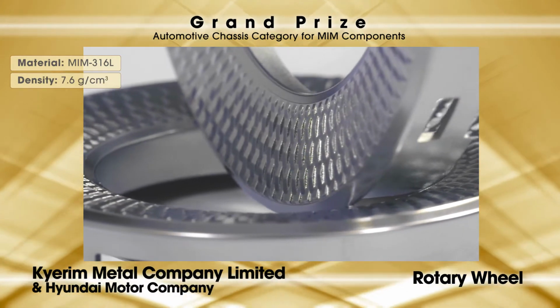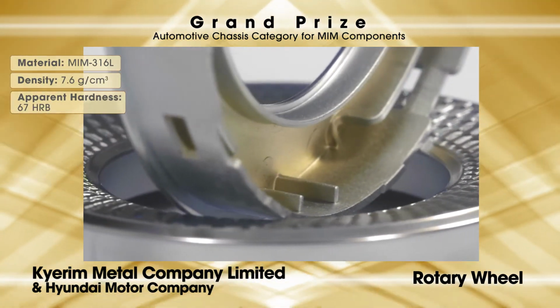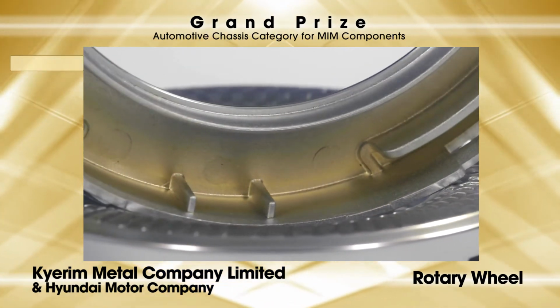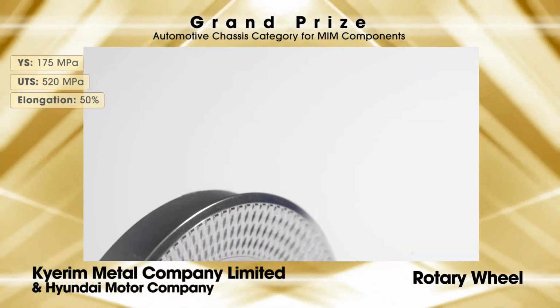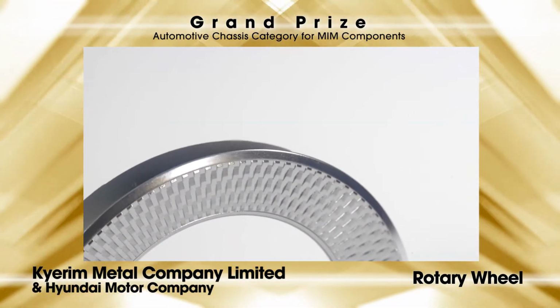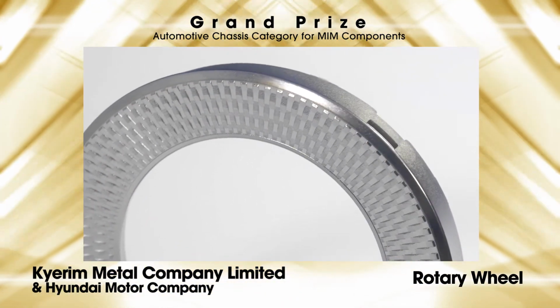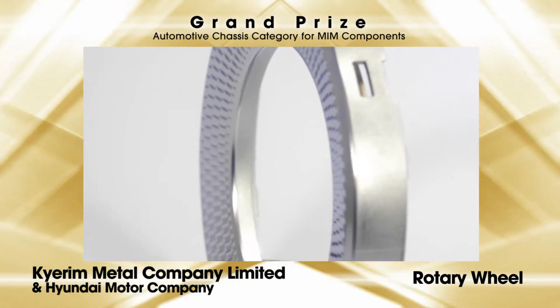The component is made from MIM 316L stainless steel to a 7.6 grams per cubic centimeter density, has an apparent hardness of 67 HRB, a tensile strength of 520 megapascals, and a tensile elongation of 50%. The 81mm diameter of the wheel is rather large for MIM, and a hot runner system was employed to improve the flowability of the feedstock to ensure a full fill was achieved.